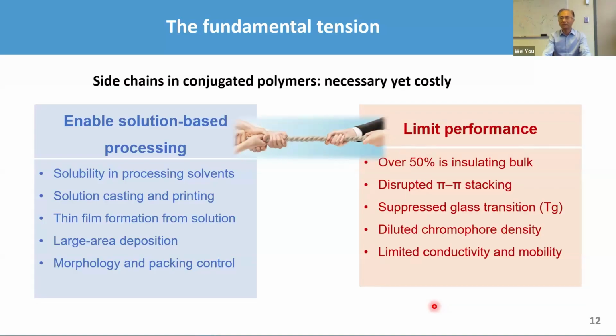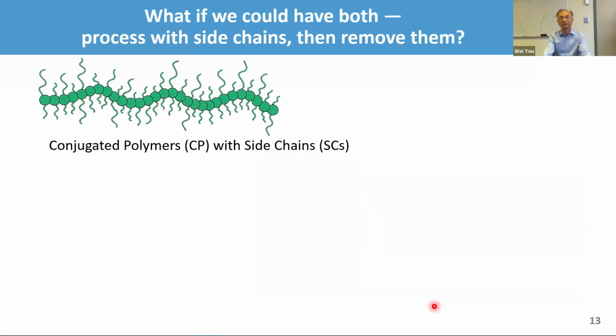But on the other side, because over 50% is insulating bulk, you now have issues with performance. 50% of the volume in the thin film is not really contributing to your conjugated polymer, which is why you're using them in the first place. So you have limited conductivity and mobility. That's the fundamental issue we're hoping to address by using some interesting approaches, which we'll talk about in the next maybe 10, 15, 20 minutes.